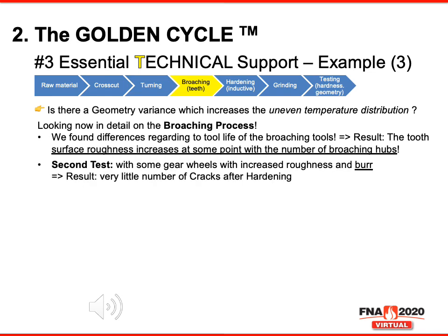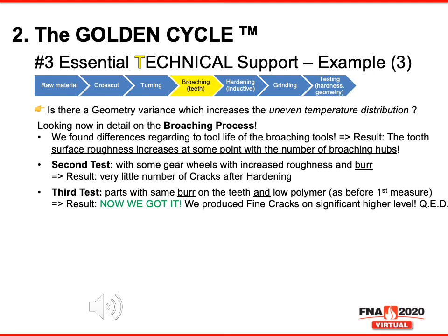So we made a second test with some gear wheels with increased roughness and burr on the surface of the teeth. The result was a very small number of cracks after hardening. So we got the second influence. The third test, parts with the same burr on the teeth and the low polymer as before in the first test, the slide before. The result was that we really produced fine cracks on a significantly higher level. Now we got it, quod erat demonstrandum, I can say.